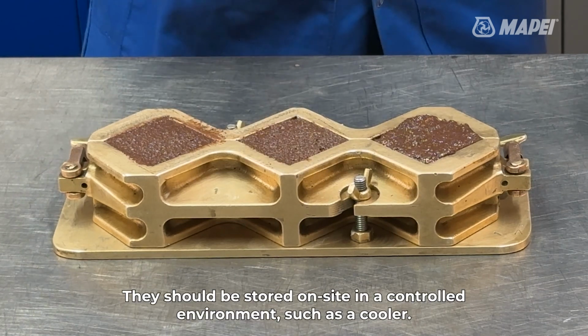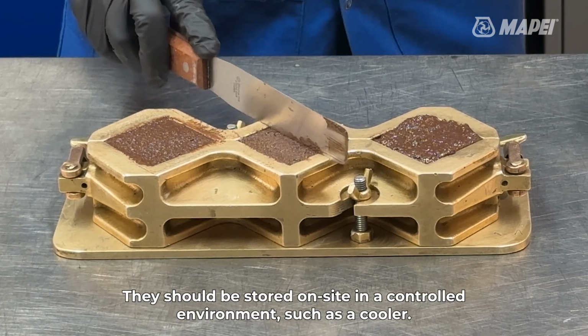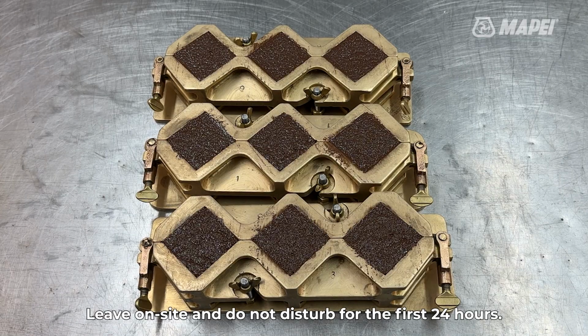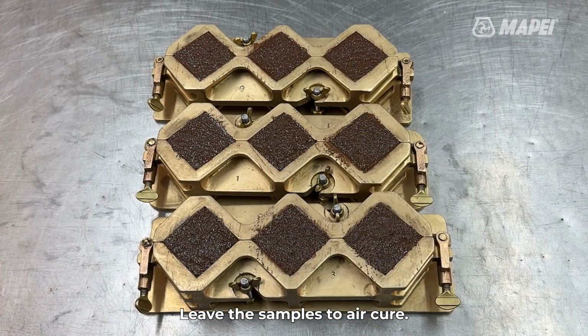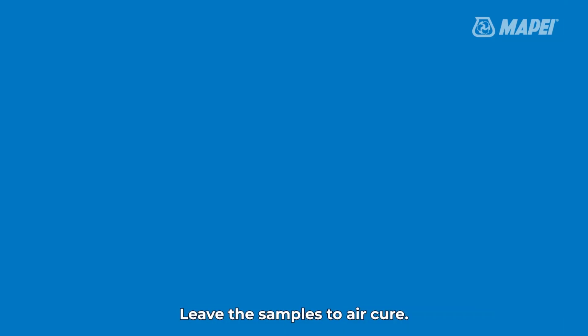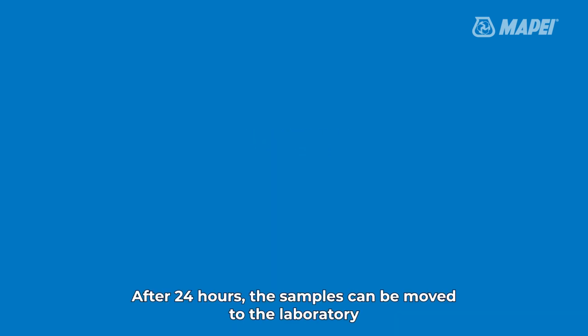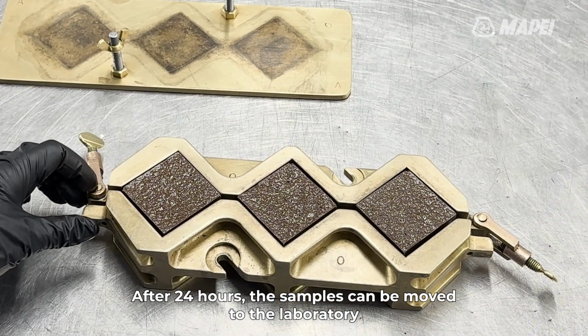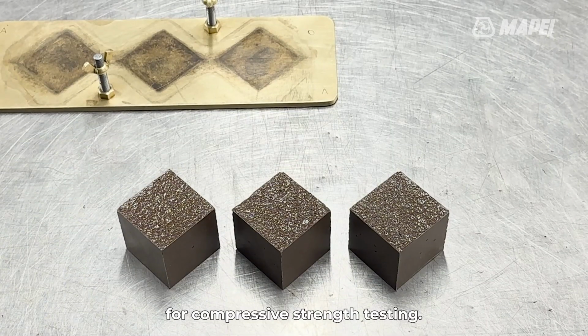They should be stored on-site in a controlled environment, such as a cooler. Leave on-site and do not disturb for the first 24 hours. Leave the samples to air cure. After 24 hours, the samples can be moved to the laboratory for compressive strength testing.